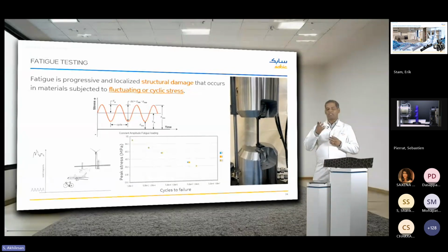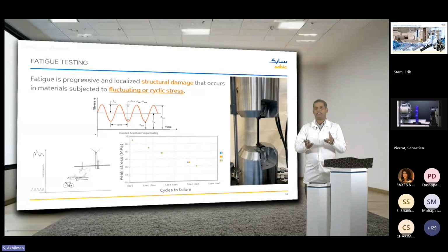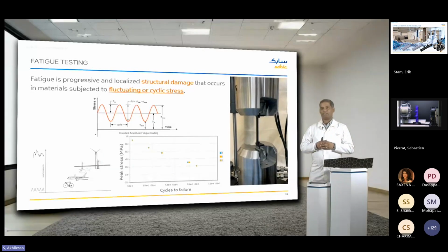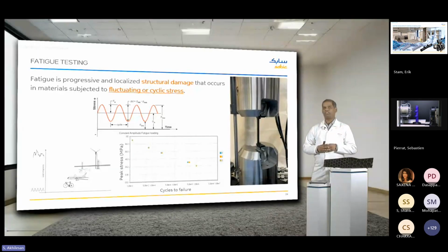Typically, to obtain data for design and simulations, we perform fatigue tests such as this on dog bone shaped specimens to apply cyclic loads and obtain the fatigue data. Data is typically generated at an R ratio of 0.1 and a frequency of about 5 Hertz. The final outcome of this test is basically the stress versus cycles to failure as shown in the graph here.